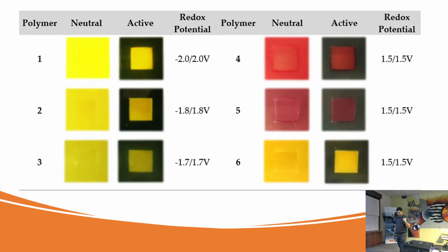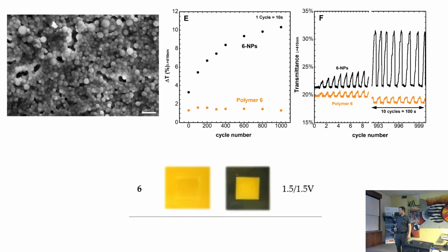The only difference is that instead of having electronic transition from yellow to one color, now we have an electronic transition from yellow to black. Okay? Because then the near infrared part counts into the visible region. And then we did the nanoparticles as well. And again, the nanoparticles behave better than the thin films. Here is the same image of the nanoparticles. And we got a very nice contrast for the nanoparticle devices.